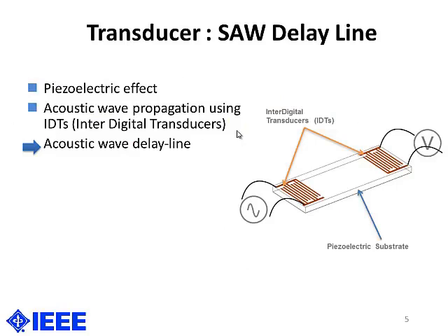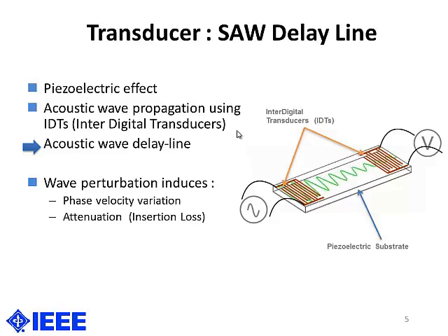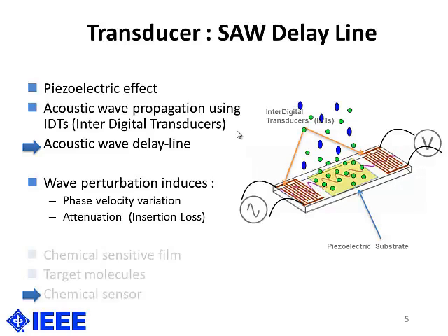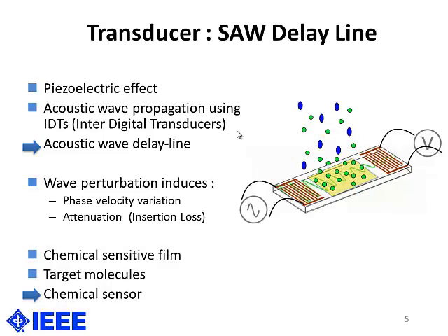The transducer is based on a surface acoustic wave delay line, that is to say a piezoelectric substrate with interdigitated metallic electrodes to generate this acoustic delay line. Perturbation of the wave induces some electrical variations of the phase velocity and/or of the attenuation. Finally, the addition of a chemically sensitive film acts as a recognition element to amplify the effect of the target compound in the solution. In fact, the main effect is due to a mechanical mass and/or viscoelastic effect.